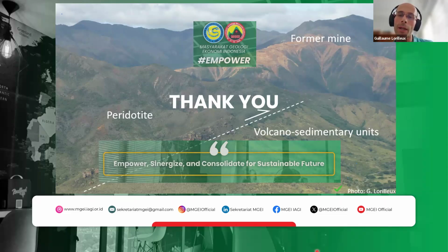But in the yellow limonite, if we go upward from the transition zone to the top of the profile, there are not much variations in density. So sometimes in estimation we can assume the density is constant. It's not always the case, but this assumption is probably acceptable.